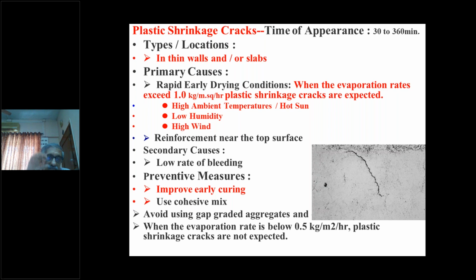So what one must do is be prepared, when you do thin walls and slabs, for protecting the concrete surface immediately. Now it is experienced that when evaporation on the surface of the concrete exceeds 1 kg per square meter per hour, plastic shrinkage cracks are expected to occur, which is generally so in almost all parts of our country, that is India. And it also includes, of course, Sri Lanka and various other places where they have reasonable winters and other seasons are only warm and hot summers.